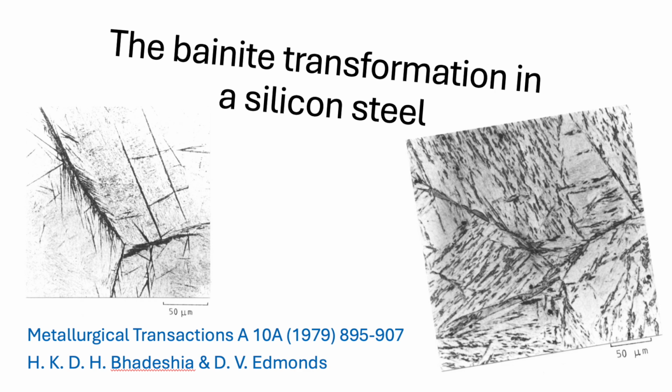And the trapped supersaturated carbon provides that stress. Precisely. Dissolved carbon drastically increases the strength and internal stress of the ferrite lattice. They estimated the supersaturation in the LB ferrite to be around 0.25 to 0.38% carbon, enough to potentially trigger twinning under the transformation stresses. It's strong mechanical proof of trapped carbon.